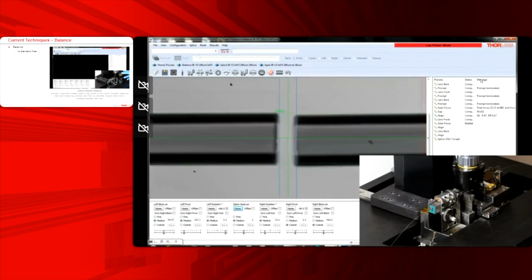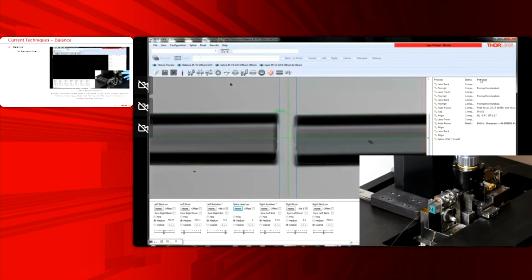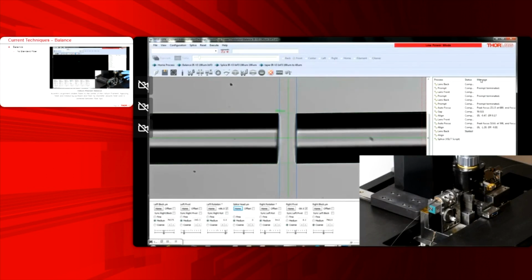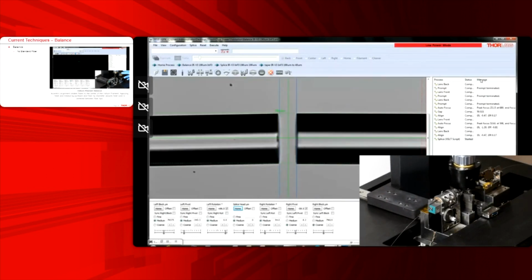Again, that heating uniformity is critical, so concentric alignment has to be done anytime you're heating, at least with this system. And iridium is going to have a longer lifetime than either tungsten or graphite. Usually iridium is good until you break it, either by accidentally putting in too much power or heating up the glass so much that you drip glass onto the filament.